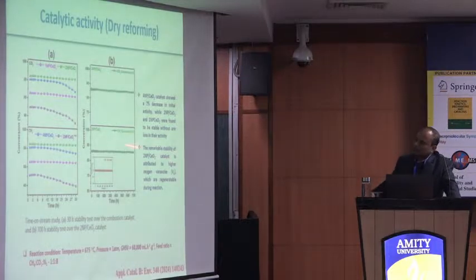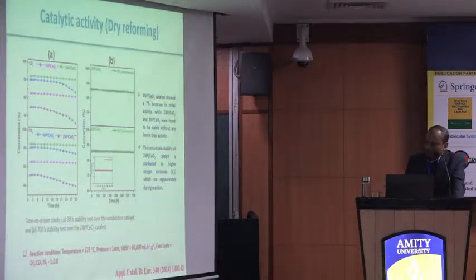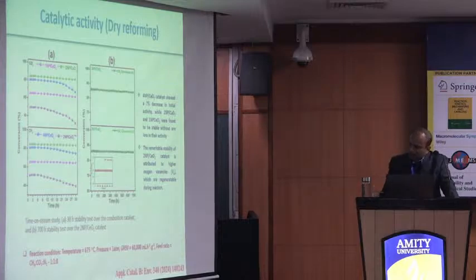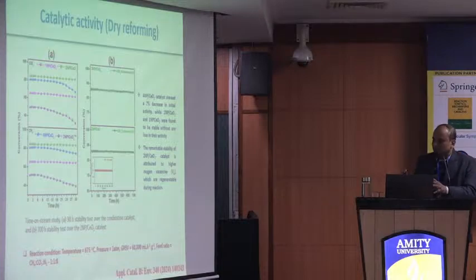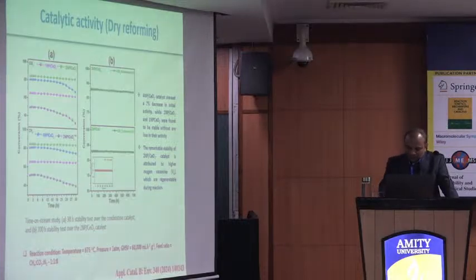You can see here the catalyst is highly stable. Up to 700 hours, there is no deactivation of the catalyst. And typically, we have done this at 60,000 ml per hour per gram. That means very high space velocity. We have done this reaction.